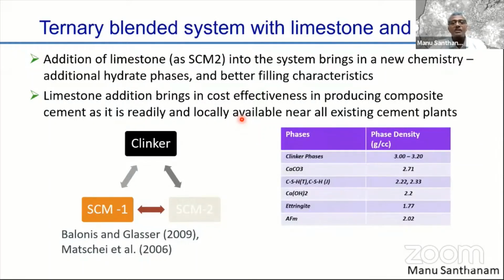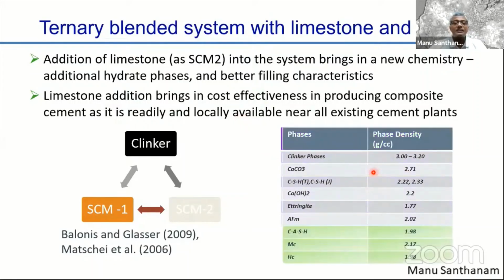Now, if you look at normal cementitious phases, they are typically higher density phases. But when you start replacing cement with alternative materials like limestone plus calcined clay together, you start producing other phases which are lower in density, as you can see from these green phases here. When you start producing phases that are lower in density, you start occupying more volume in the system. And when you occupy more volume, obviously you're causing a reduction in the pores present in the system. So as you reduce the pores, your strength is going to go up and your durability also will go up because many of these pores will start getting disconnected.